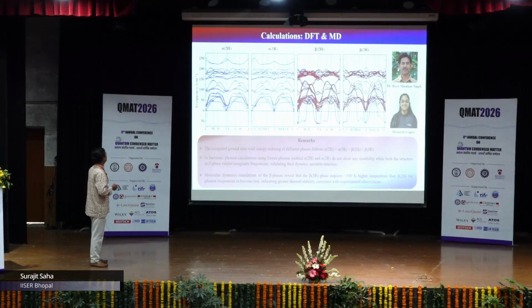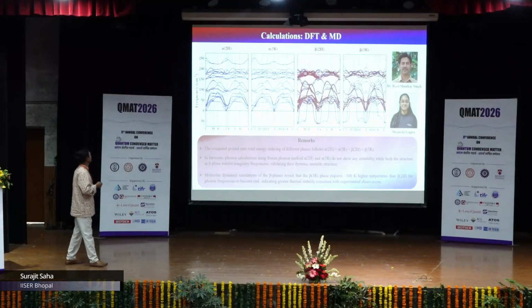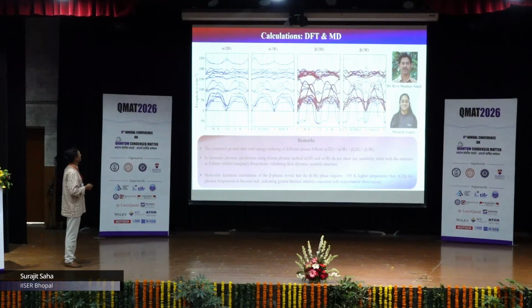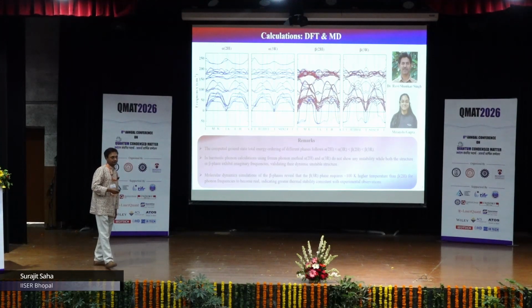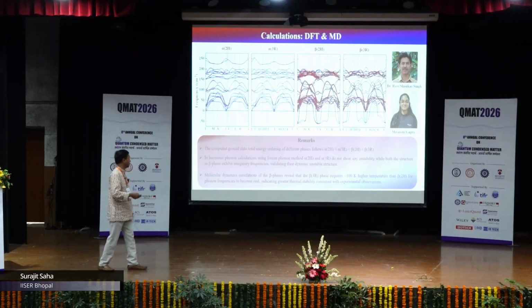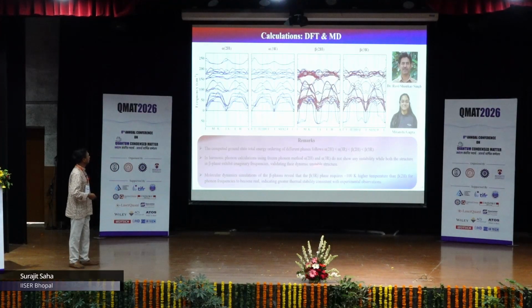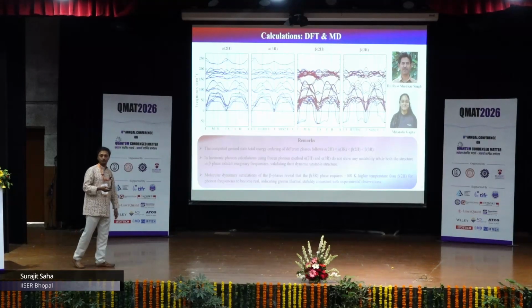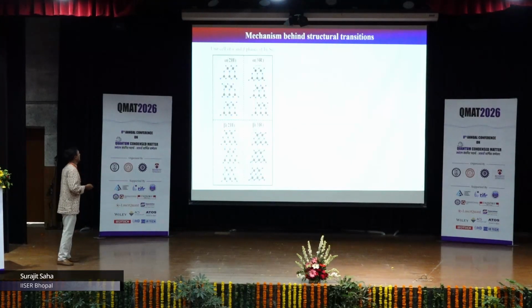Here you can see the phonon dispersion relations. Both the alpha 2H and alpha 3R show stable phonon dispersion relations, but for the beta 2H and beta 3R, the blue curves you can see, they are unstable at 0 temperature. Only when you go to much higher temperatures do they stabilize. So that basically supports what we could find experimentally.